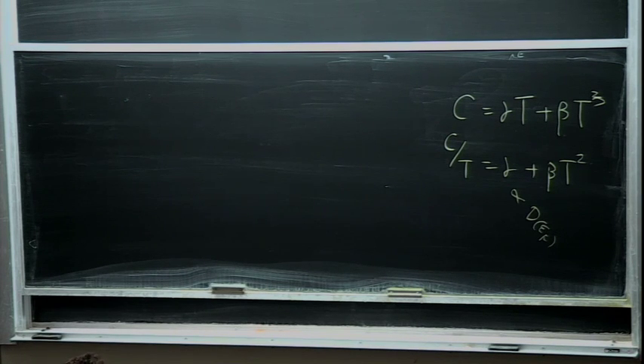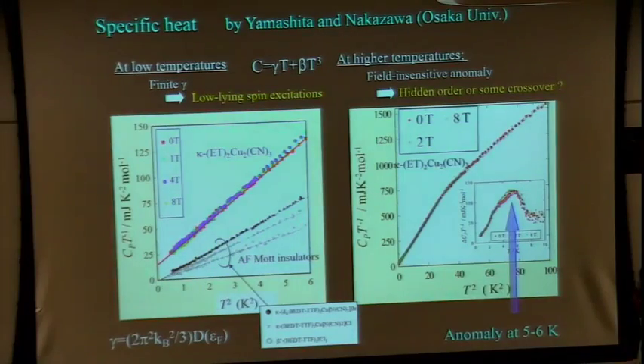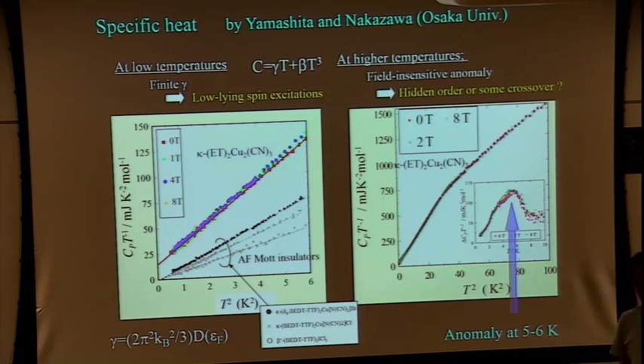The textbook says that for insulating materials, the gamma term, namely the intersection, should vanish. And the data plotted in this figure is for insulators. All of the materials are insulators. Antiferromagnetic Mott insulators show vanishing gamma as expected. However, the spin liquid material, although an insulator, seems to show a finite gamma. This Osaka University group extended the measurements down to lower and lower temperatures, the millikelvin range, and they confirmed that the gamma is finite. Anyway, finite gamma.